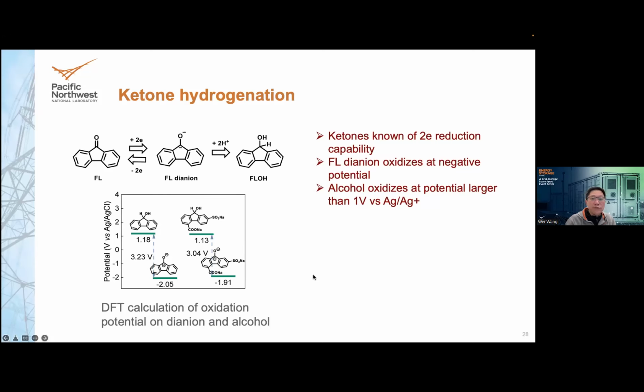So actually, the fluorenone is a ketone structure. The ketone is known for its 2-electron reducing capability, very facile reaction. But the dianion will oxidize at the electrode potential. Then it forms alcohol. The alcohol, if you want to bring it back, the potential will be much higher, over 1 volt versus silver chloride. So you basically cannot use it as an anolyte anymore. That's basically the reason why the capacity in the aqueous system drops so much.